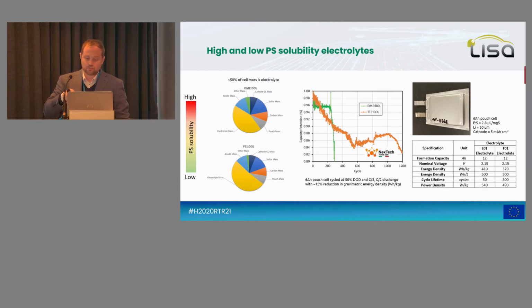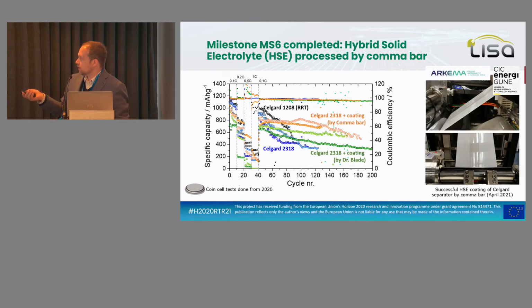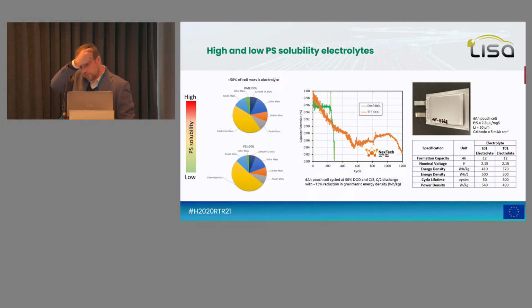Here you have 2 configurations, one at more than 400 watt-hour per kilo, the other at 370 watt-hour per kilo. So this is what you can get in terms of cycle life, depending on how you make your cell work, no? Basically, I did not go into detail, but Nextech has a different strategy from what we have done here regarding the solubility of polysulfide. I will not go into detail, but if you have a different density of cathode, you have to adapt your electrolyte too, and so you can promote high solubility of the polysulfide or clustering of the polysulfide, no? And if you go in one direction or another, you have one result or another.